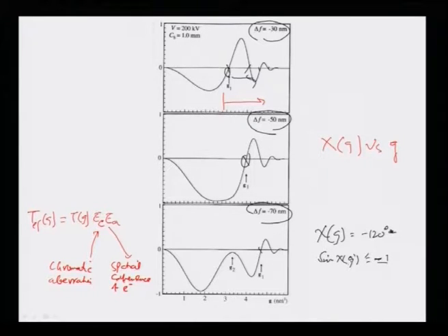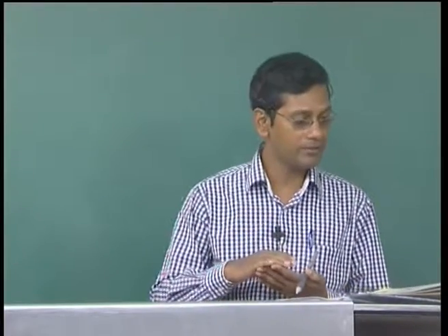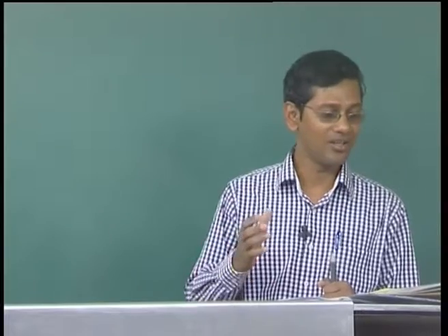This effectively means the envelope function is basically acting as a virtual aperture in the back focal plane of the objective lens, regardless of whatever the value of the defocus. That is the actual meaning of that. So, that means physically, if we at all put an aperture in the back focal plane to remove this unwanted noise, this must be less than the size of the virtual aperture present because of this